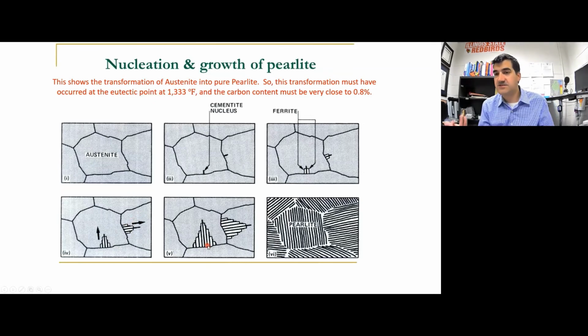And it's just like grain formation. So your grains actually kind of regrow from the austenite material. You've got ferrite and pearlite grains that actually grow from and inside the grains of austenite. And this is our final product. All I can see here are pearlite grains. So we know because of that, because this evidently is all or at least mostly pearlite, this must be pretty close to a 1080 steel, something pretty close to that.